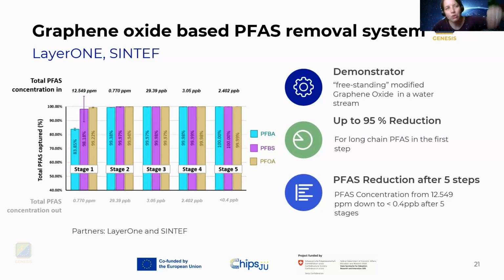You can see it flows through the first stage. And in the light gray color at the bottom, you can see it's already reduced quite a lot. So now it's only 0.77 ppm. That means after the first stage, getting this PFAS contaminated wastewater running through a so-called freestanding graphene oxide, it was possible to show that they can reduce it up to 95% already. You can see three different colors because it has to do with what I mentioned before, that the chain length of PFAS defines not only the sensing, but also what you need to use for absorption. So here they found out that the absorption is better for long chain compared to short chain.